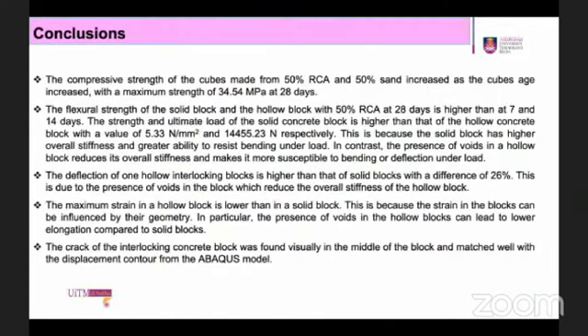In conclusion, the compressive strength of the cube made from 50% RCA and 50% sand increases as the cube age increases, with a maximum strength of 34.54 megapascal at 28 days. And then the flexural strength of the solid block and the hollow block with 50% RCA at 28 days is higher than at 7 and 14 days. And then the deflection of the hollow interlocking block is higher than that of the solid block, with a difference of 26%.